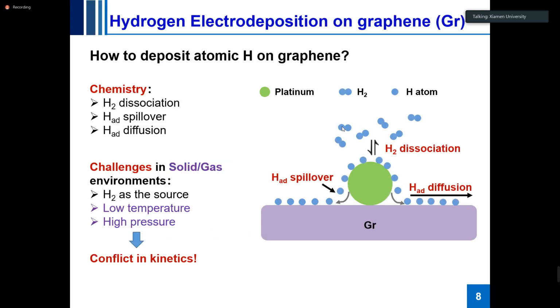So how to deposit hydrogen on graphene? The first is the chemical route. They use hydrogen as the precursor. The hydrogen dissociates on the catalyst to form atomic hydrogen. These atoms can spill over from the catalyst to the graphene surface and then be adsorbed on the graphene through surface diffusion. The challenge in the solid gas environment is that you have to use hydrogen as the resource, and also this process should be performed at a very low temperature and with a very high pressure. This is a conflict in kinetics.